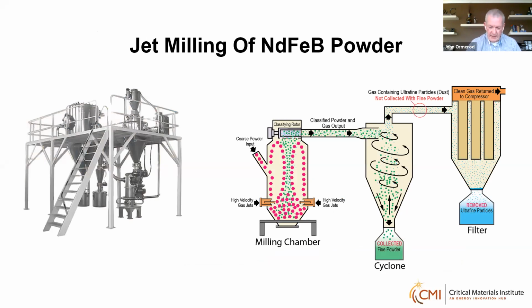which is jet milling. What this process does is it produces a very narrow particle size distribution around the target average particle size, which is required, and at the same time removes harmful ultrafine high rare earth content particles. So in my view, all these three upstream processes have really contributed to the excellent magnetic performance we see in sintered neodymium-iron-boron based magnets, and indeed the market acceptance of those materials.